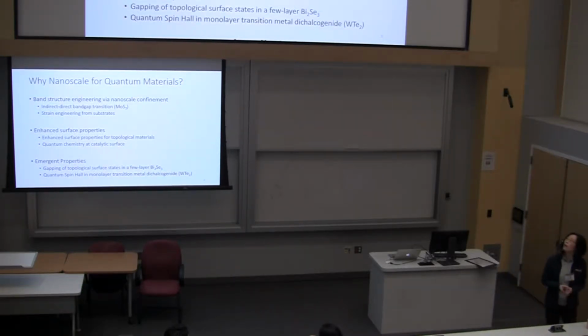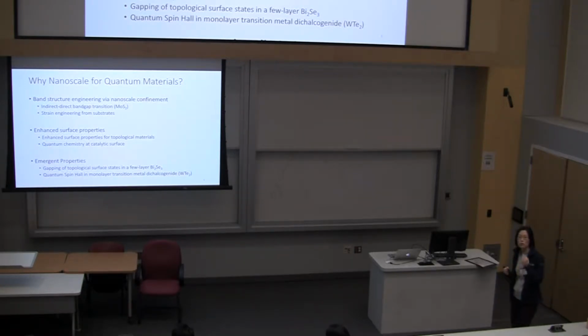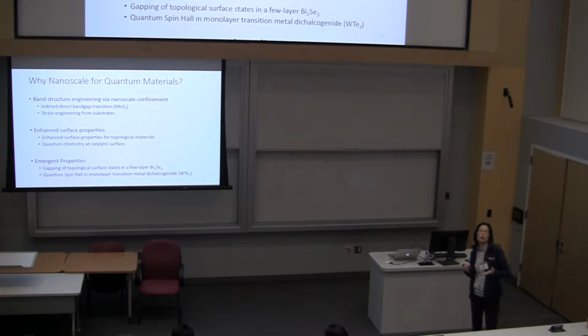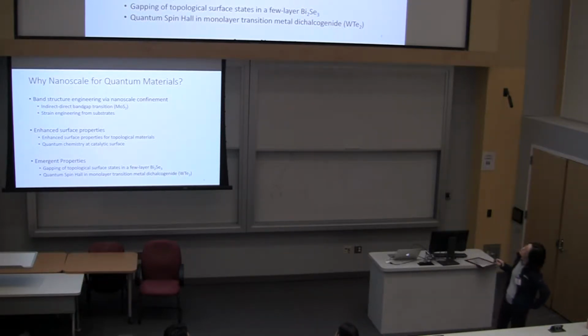Okay, so why nanoscale? Some of this we all know. Band structure engineering, right? We know that the band gap gets larger as you confine your materials. It's a classic particle in a box type problem. As you shrink the size of the box, the spacing between the levels gets larger, and the band gap then increases. And in some way, as you shift around the band edges, it can also have an indirect to direct band gap transition. We know this for molybdenum disulfide, and that makes a big difference in optoelectronic applications because there's a good coupling between electrons and photons that way.